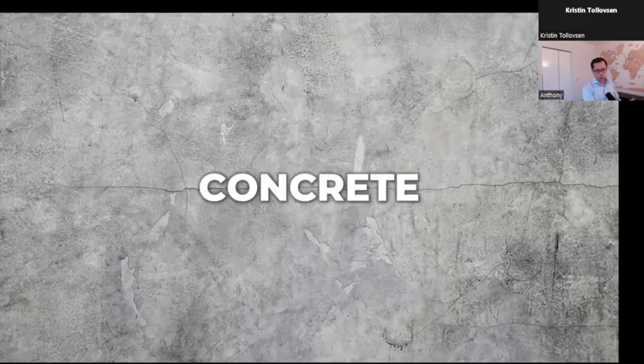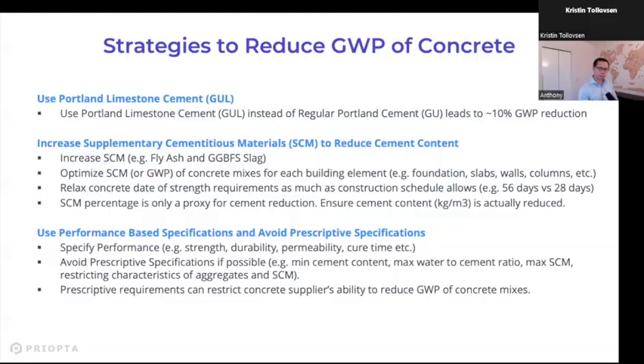So for concrete, what can you do? This is oftentimes probably the highest impact material on most projects. Well, first off, you can look for Portland limestone cement, also known as GUL, general use limestone. Use this instead of just regular Portland cement. Oftentimes this is low hanging fruit, not much performance impact. You can get about 10% reduction per meter cubed of concrete just by switching out the cement, where they essentially add more limestone into the cement. And in some regions, like in Metro Vancouver, this is already standard practice, like most concrete is GUL in Vancouver.